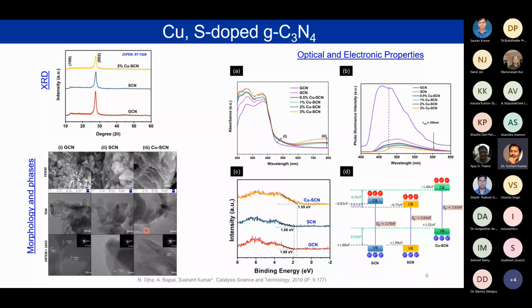Now, besides these facts, we went on to study the optical and electronic properties. Here you can see the band gap; this plot is for the UV-visible DRS. The band gap has not changed drastically. What has changed is this effect. What is this effect? It is the plasmonic effect. Copper in general shows the plasmonic effect, and that helps in activating the photocatalyst to have more electrons on the surface, which helps in more product formation.